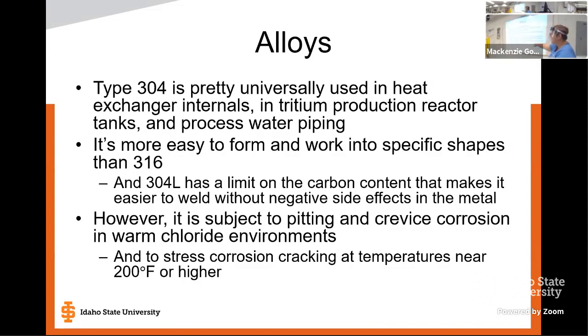However, in warm chloride environments, it's susceptible to pitting and crevice corrosion. So this is a material that you would have to ensure does not have low or stagnant flow conditions that can start creating pitting or crevices, right? At around 200 degrees Fahrenheit and higher, it's also susceptible to stress corrosion cracking. So your very high temperature side of the nuclear plant, this is not necessarily the first choice, but a lot of the warm side of the plant where you need good structure material, this is a good choice. And it's a little bit cheaper than 316. So if you have an application where either would be acceptable, you're probably going to see 304 get chosen because it's a cost savings. Any questions?